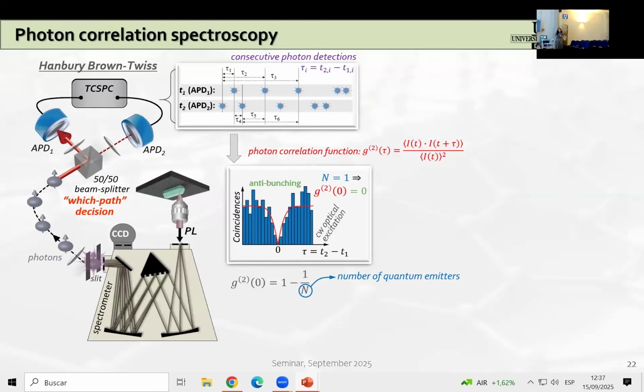Now, what we then wanted to do is to ensure that we are really dealing with quantum light. For that, we basically filter out the emission of a nanowire quantum dot using just a single grating spectrometer, and the signal is then sent to the Hanbury Brown and Twiss interferometer, which, for those who are not familiar, consists of a beam splitter and two single photon detectors positioned in the reflection and transmission arm of this 50-50 beam splitter. The signal from these detectors is then fed into the electronics, which delivers such histograms of correlation events as a function of time delay for the consecutive photon detection at both detectors. These histograms are proportional to the second order correlation function.